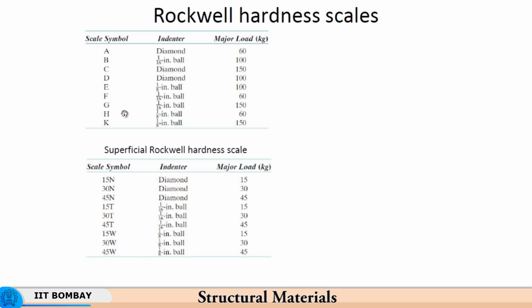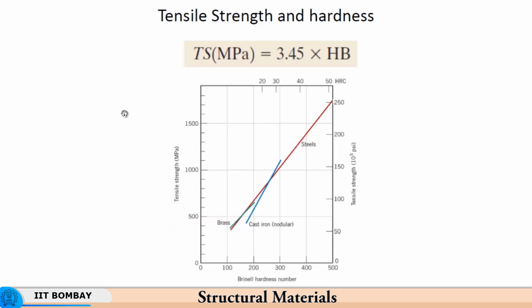So, sometimes you want to do a micro hardness test. So, you want to find out the hardness of the case carburized layer. So, you do not want to go too deep into it, otherwise the indenter will just penetrate through the case and then again measure the hardness of the parent metal. So, you want a superficial hardness, for which the Rockwell scale is given for relatively lower loads. You do not apply the loads which are used for a normal Rockwell test, lower loads are used for superficial hardness. So, now the tensile strength and hardness are related.